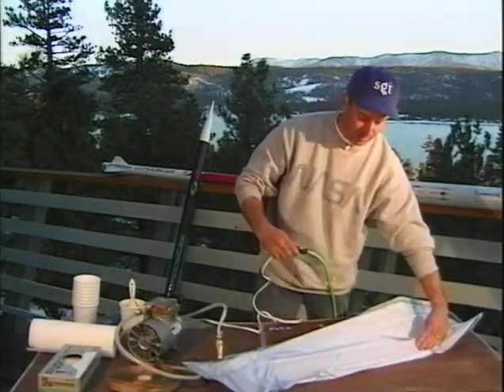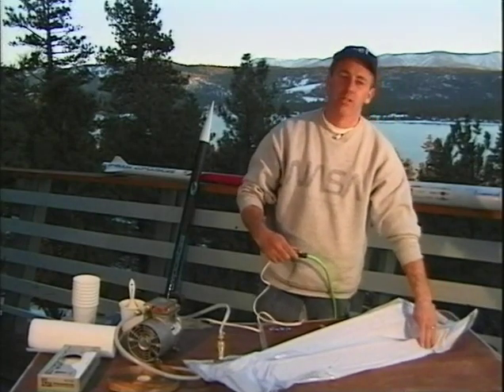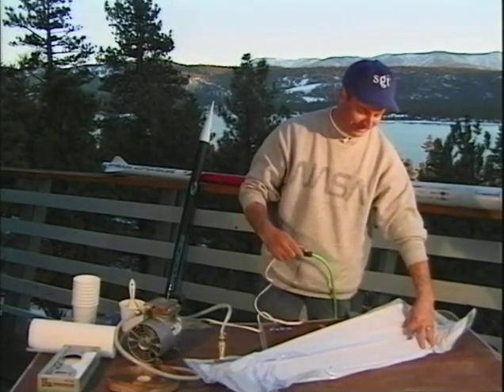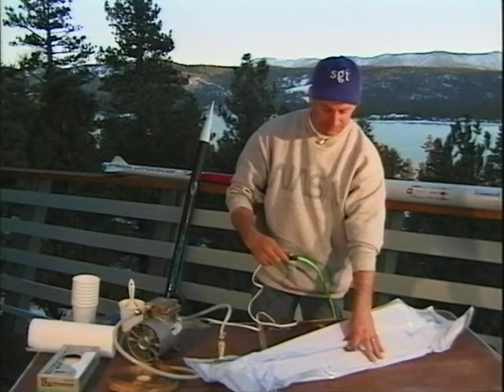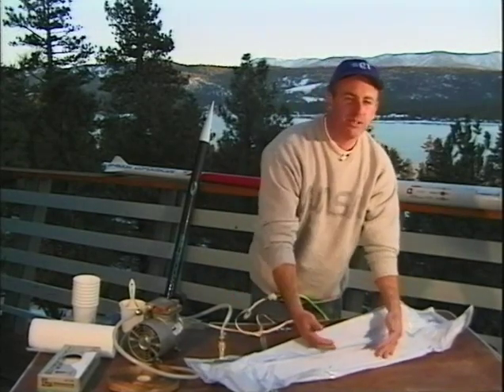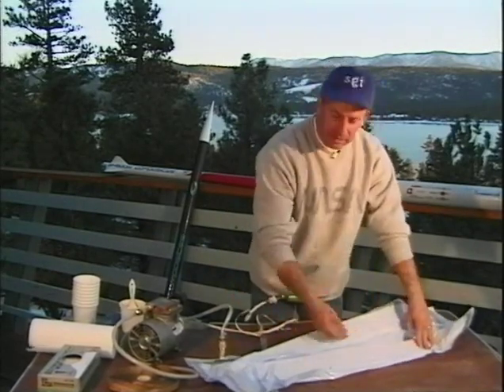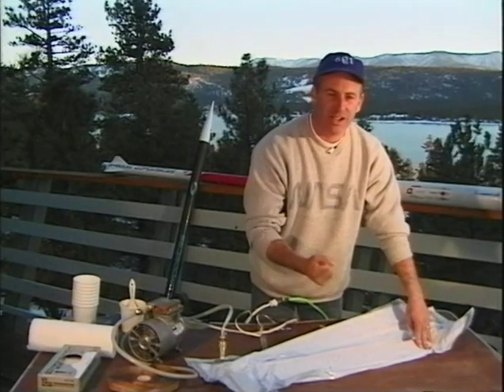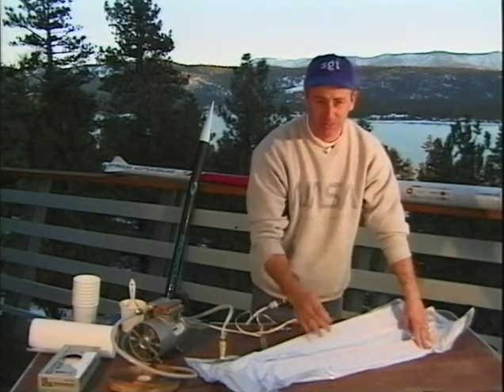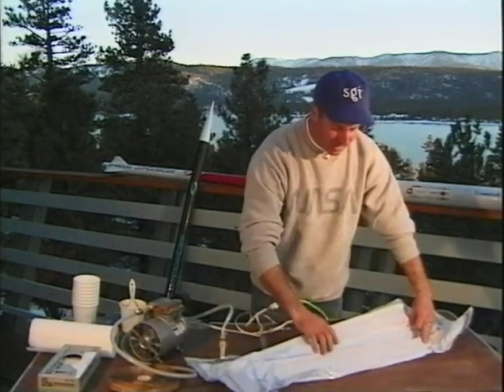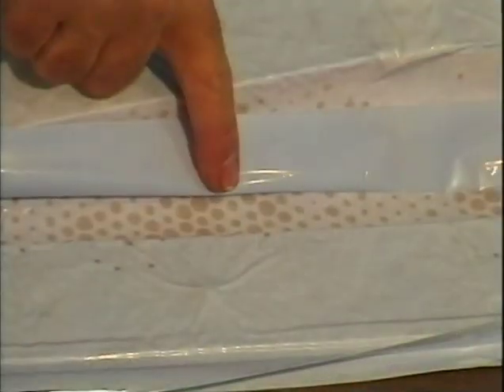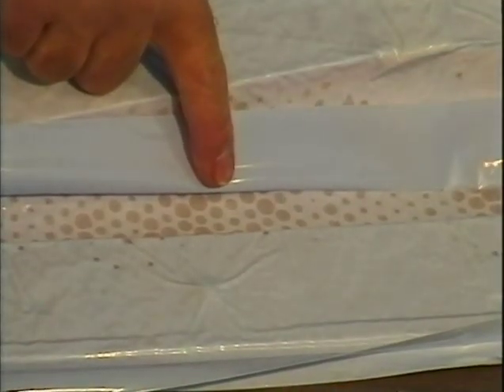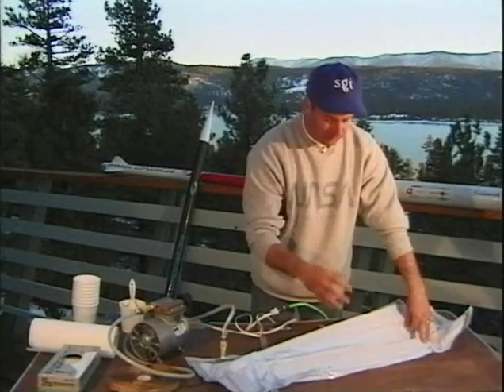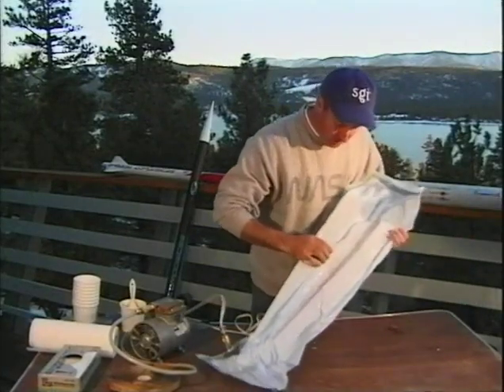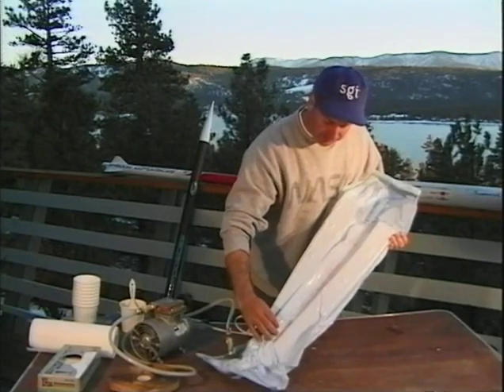And now it's starting to pull down in. And look at it go. All right? It has now pulled all the laminate into real intimate contact with the rest of that surface coat that was in the mold. You can see also with the perforated release layer, that resin's starting to come up. The excess resin is starting to come out of the laminate. All right? Pull it up so you can get a real good look at it.